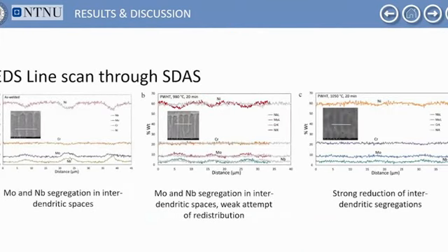About the redistribution of the elements, the most important elements for the corrosion resistance, we performed EDS line scan through the secondary dendrite arm spacing, and we found a segregation of niobium and molybdenum in the interdendritic zones, and in the opposite way, nickel was depleted in this zone.